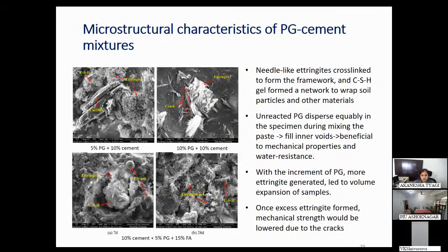So again, this group of researchers looked into the microstructure to answer these questions. And as I have already briefed, if you see these needle-like particles, these are ettringite, which are formed due to the phosphor gypsum and Portland cement reaction. And this is CSH gels. And these ettringite wrap the CSH gels, the soil particles and the fly ash particles, with the 5% phosphor gypsum and the 10% cement.